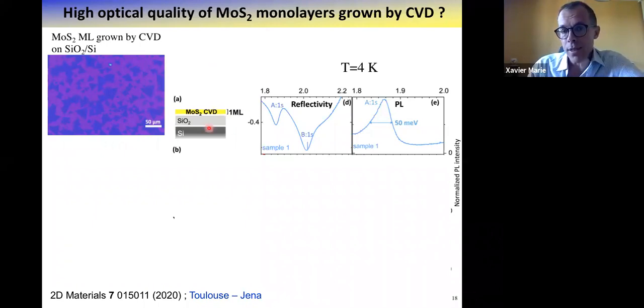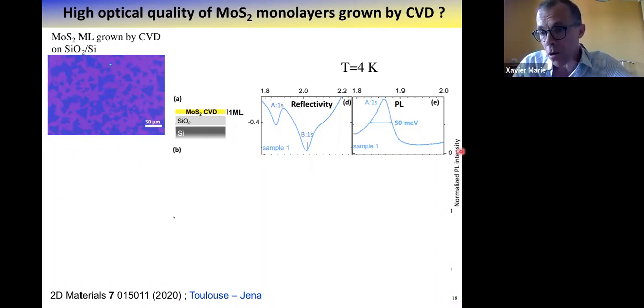So it was grown on silicon oxide silicon. It's a collaboration with the group of Andrei Turchanin in Jena. And what we have done, so first we have characterized this CVD monolayer. You see, it's the reflectivity, even at low temperature, you have the A and B transition, very broad. Photoluminescence, again, at low temperature, 50 millielectron volt line widths, very broad again.